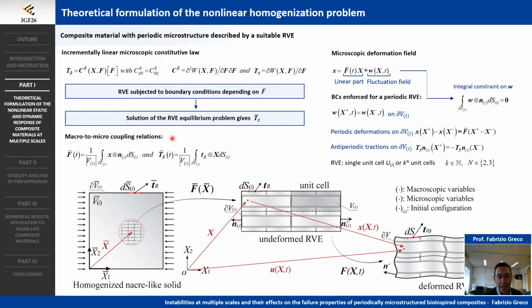The micro and macro scales are in fact coupled to each other by means of the classical relations that define the macro variables in terms of deformation and traction on the boundary of the RVE. By splitting the microscopic deformation field into a linear part plus a fluctuation field, it follows that an integral constraint must be imposed on the fluctuation field, and according to the periodic nature of the material, this constraint can be satisfied by enforcing periodic deformation on the boundary of the RVE and antiperiodic traction.